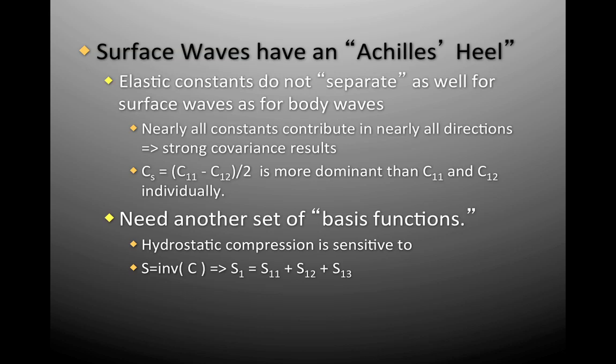What we need is another set of basis functions, another set of constraints, and Ross Angel measured high precision hydrostatic compressions, which are sensitive to the compliance matrix, the S as an inverse of C, and the X-ray determinations of compression determine components like S1, which is the sum of S11, S12, and S13.